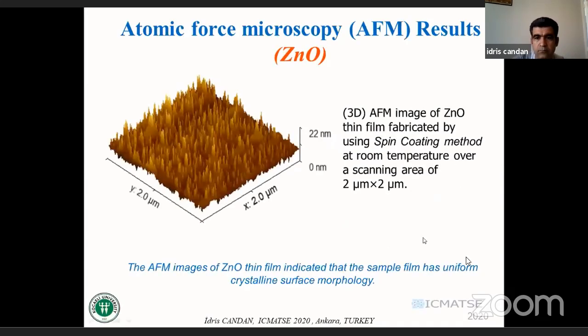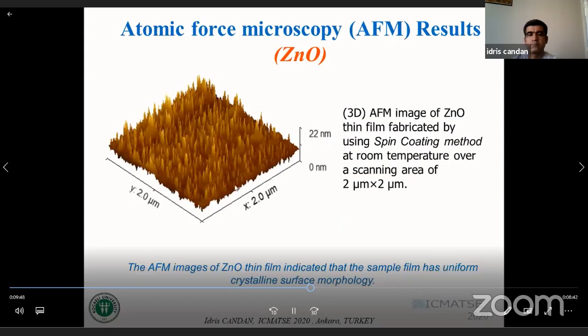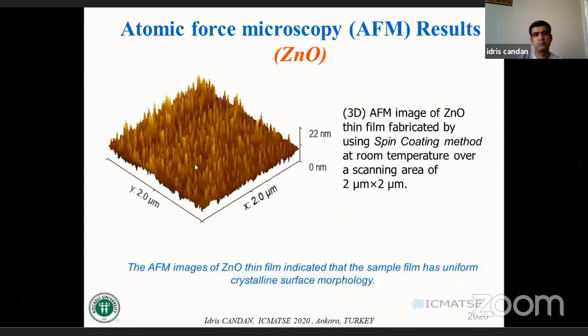The atomic force microscopy results of the zinc oxide. As you see here, we get a three-dimensional image of zinc oxide using the spin coating method at room temperature over the area of 2 micrometer by 2 micrometer. The average roughness of zinc oxide was found as 1.32 nanometer. The AFM image of zinc oxide thin films indicated that the film has uniform crystalline surface morphology.